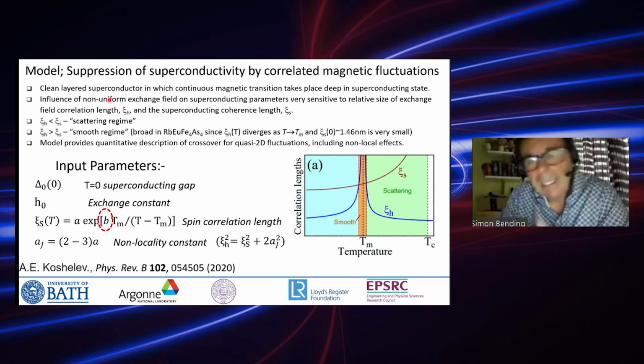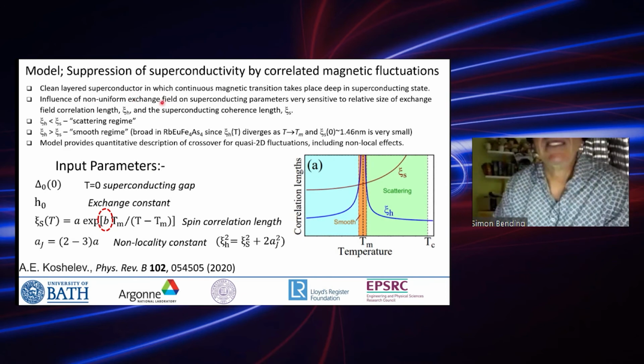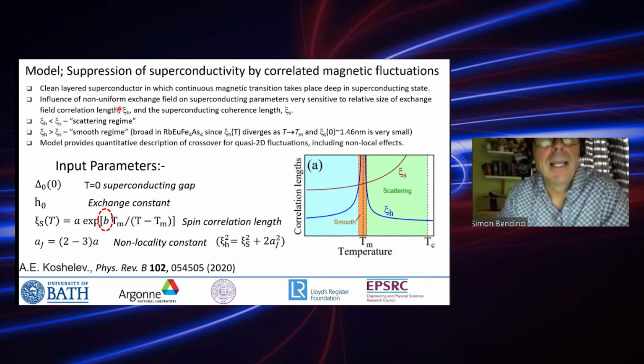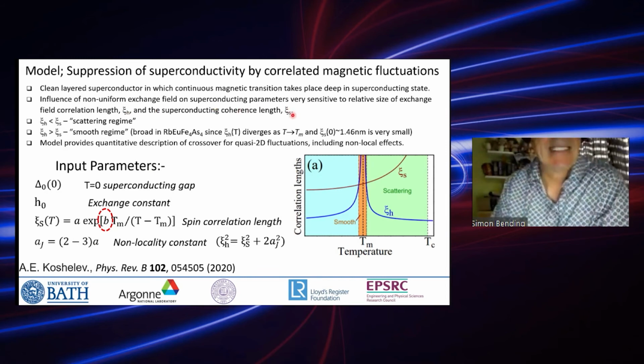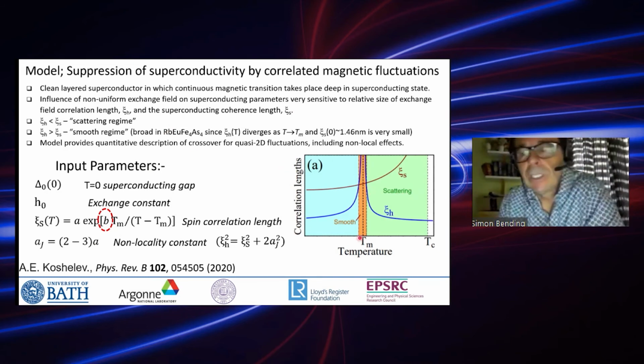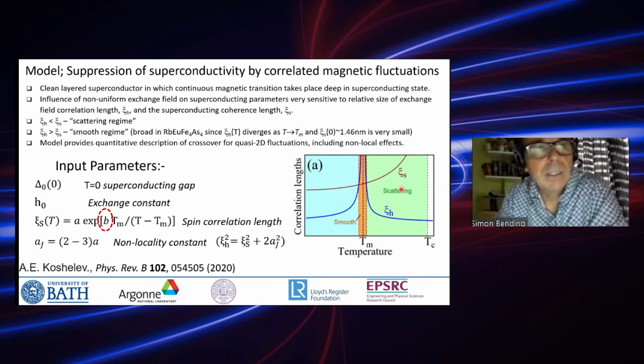And the interaction between the magnetic and superconducting states depends very sensitively on the relative length scales that are involved in the problem, in particular the size of the exchange field correlation length, ξ_h, and the superconducting coherence length, ξ_s. And really there are two regimes, which are sketched in this diagram here. This shows the two correlation lengths as a function of temperature. And up in this green regime, which Alex has called the scattering regime, we have the case where the exchange field correlation length is much smaller than the superconducting coherence length. And this is very much like the situation that you have in the case of magnetic impurities, scattering off magnetic impurities in a sort of a doped superconductor.